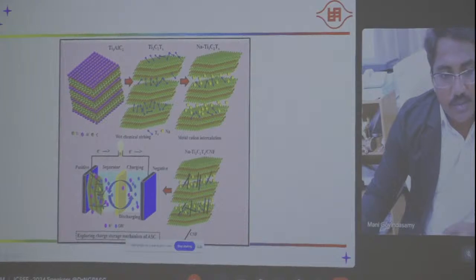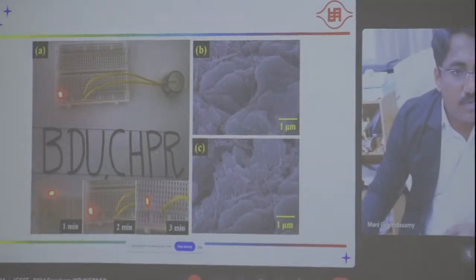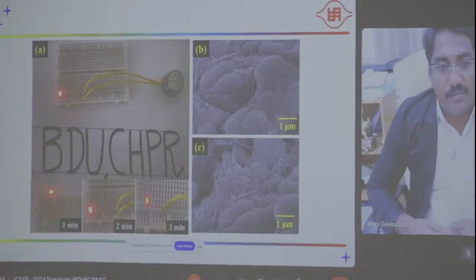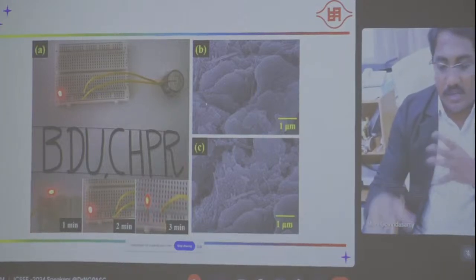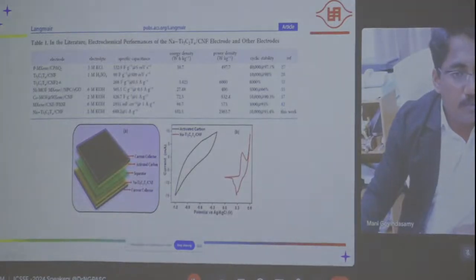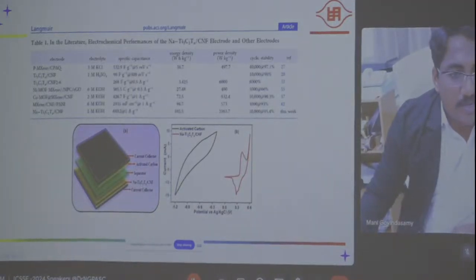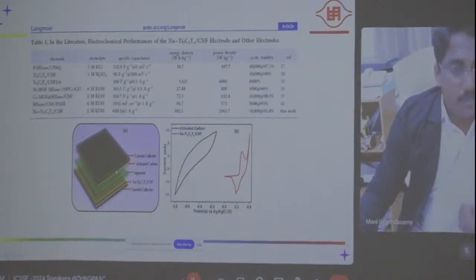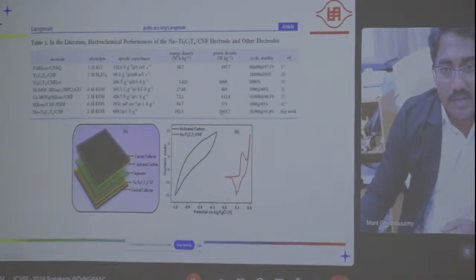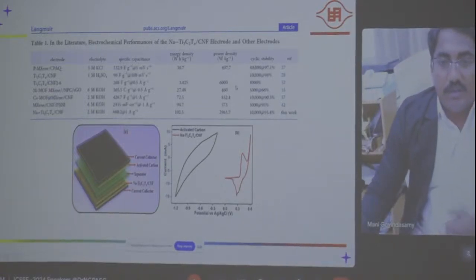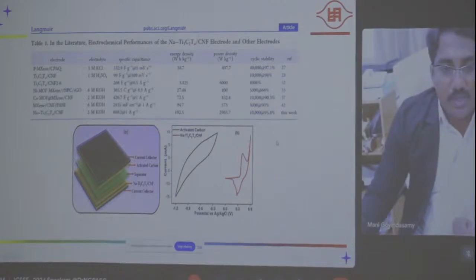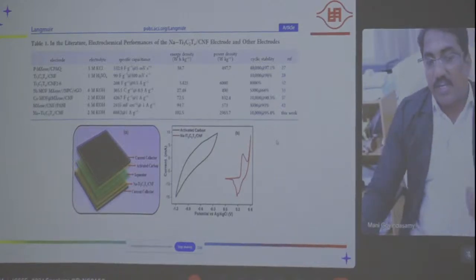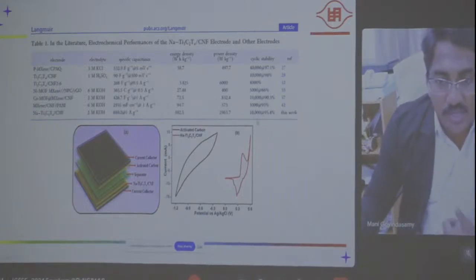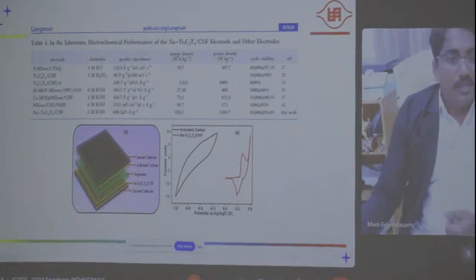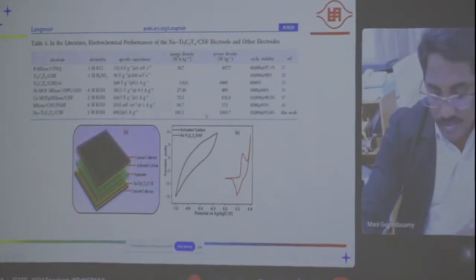For example, here we use the coin cell asymmetric supercapacitor for the device application. Here we can even develop a multi-layer coin cell supercapacitor, and we get the energy density as well as power density. This is the procedure for the current collector, activated carbon, separator, material, and current collector. This is the simple fabrication technique for supercapacitors. With similar materials we can get around 3000 watts per kilogram. This is better performance compared to the previous titanium based MXene materials. This work also runs around 10,000 cycles and is more stable, at 95.4%.